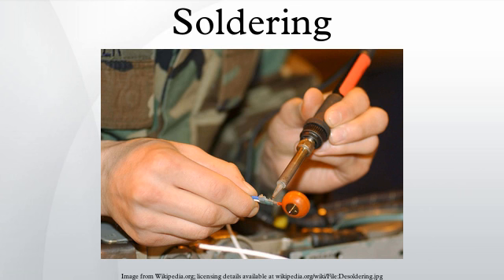Copper tubing conducts heat away much faster than a conventional handheld soldering iron or gun can provide, so a propane torch is most commonly used to deliver the necessary power. For large tubing sizes and fittings a MAPP-fueled, acetylene-fueled, or propylene-fueled torch is used with atmospheric air as the oxidizer. MAPP oxygen or acetylene oxygen are rarely used because the flame temperature is much higher than the melting point of copper. Too much heat destroys the temper of hard-tempered copper tubing, and can burn the flux out of a joint before the solder is added, resulting in a faulty joint.